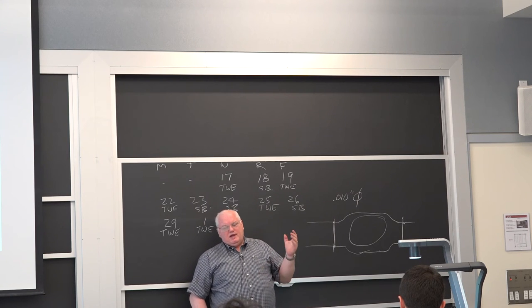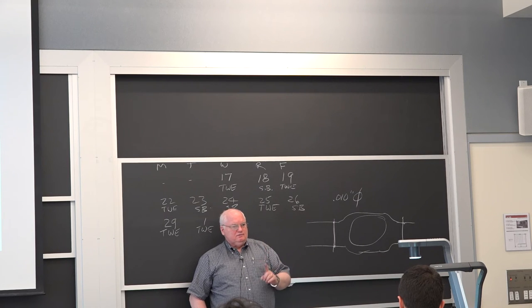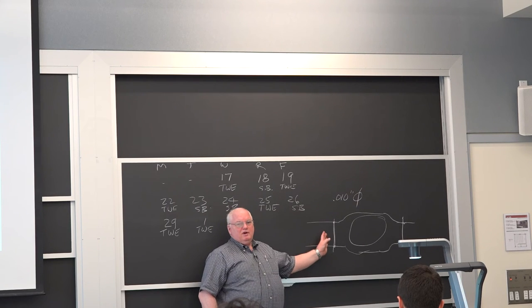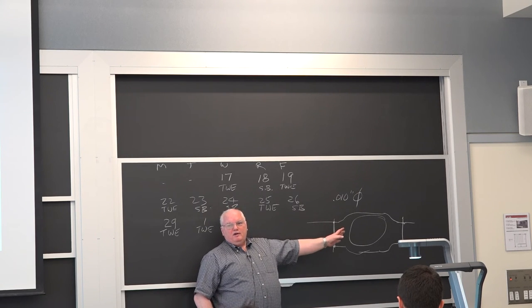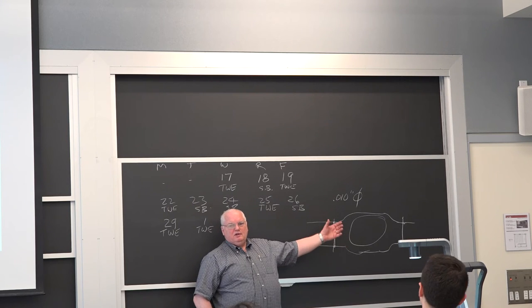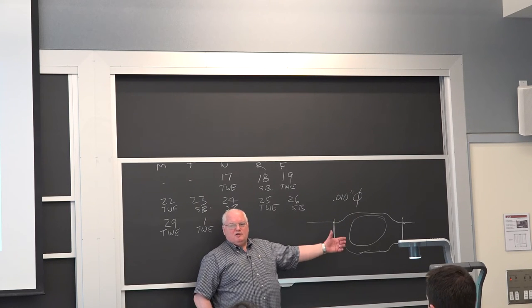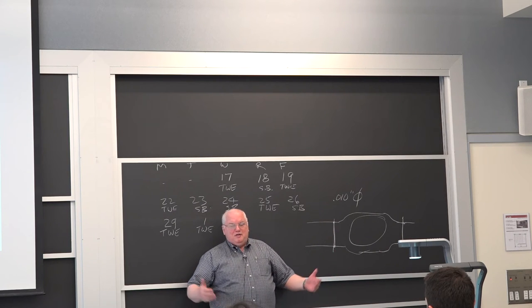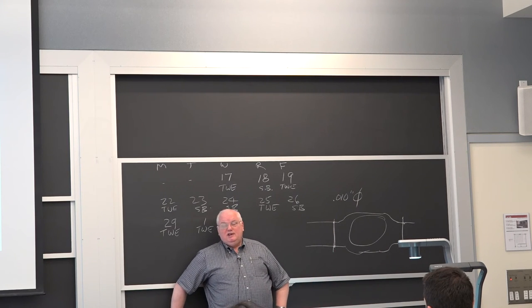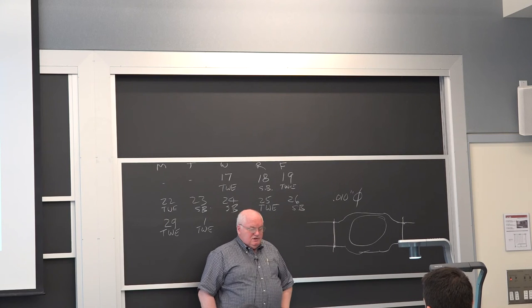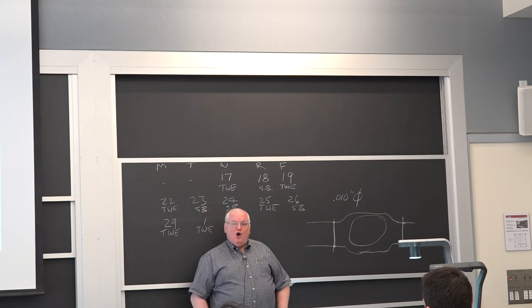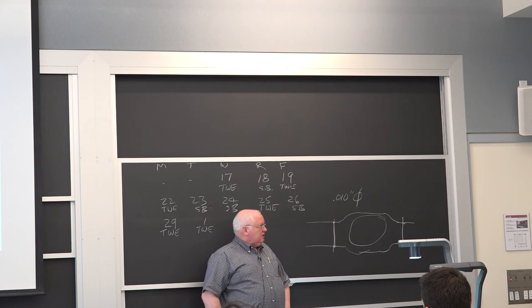And if it was larger than 10 thousandths of an inch, they had to cut it out and re-weld it, and they only got one chance to re-weld it. You couldn't do two re-welds, okay? So the odds were you're going to have one failure, and then when you cut the whole thing out and try to weld again, the odds are you're going to have another failure. So they had not been able to produce any of these units for Boeing, and it was going to hold up the whole rollout of the aircraft. And people were getting very upset and very concerned.